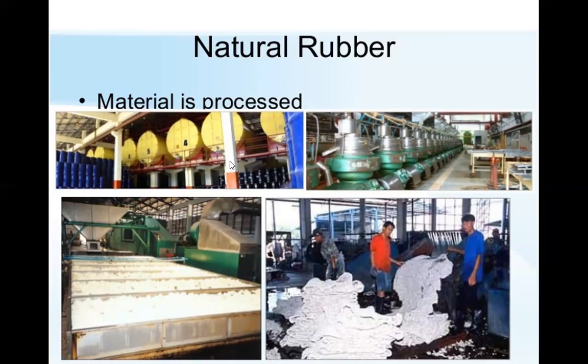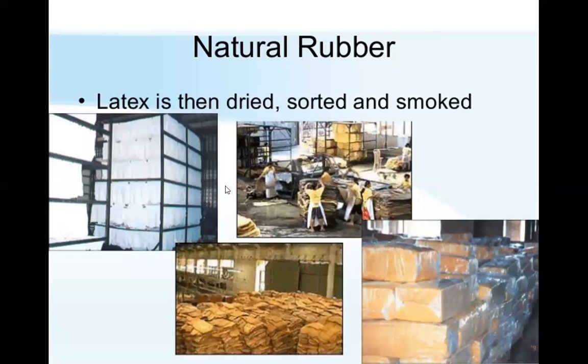After that, the coagulum is passed into rollers about 3 mm apart and 50 centimeters wide, and it is extruded in the form of sheets which resemble crepe rubber and possess a rough surface.